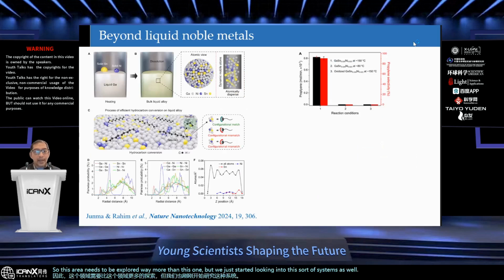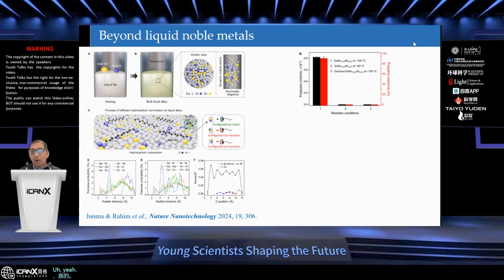So as I said, liquid metals can provide you surprises, and this is one of them. We published this paper last year, and possibly you have seen this. We looked at two metals dissolved in gallium, nickel and tin, in gallium, and we wanted to get some oil, like a long hydrocarbon chain, and see what they produce or whether they can be catalyzed. It's a very straightforward system. You mix them, heat up to 200 or something, look at the hydrocarbon, its vapor pressure, its vapor range, that when it starts to vaporize, if you're within that limit, that's fascinating.